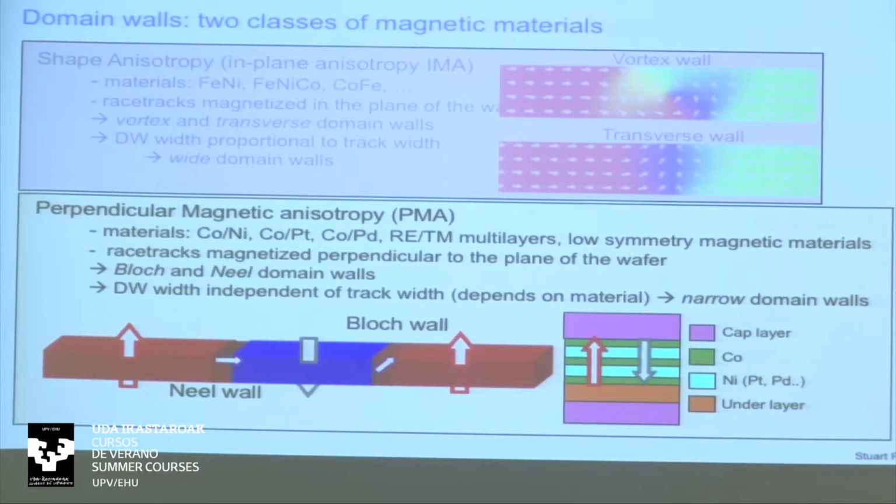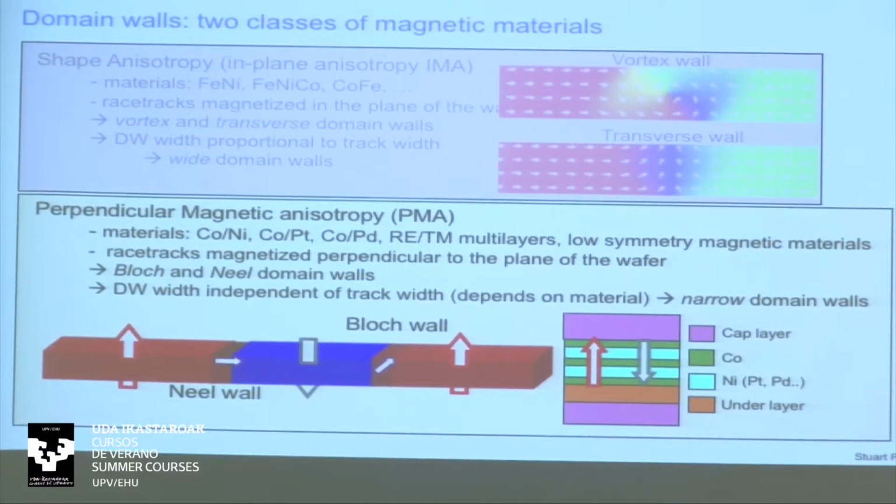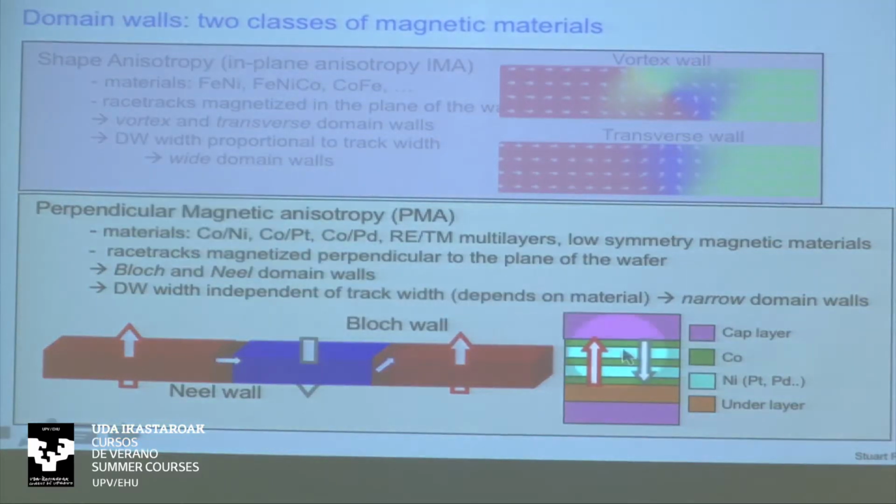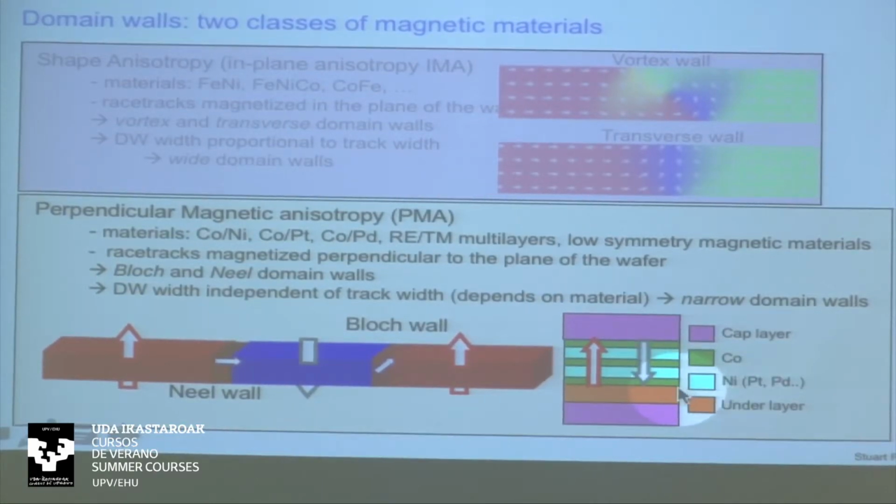So it turns out, I want to discuss this. It's a little bit technical, but nevertheless, I think it's interesting. So you basically have a racetrack which consists of these wires. The green is cobalt. These are like 1 to 3 angstroms thick, separated by nickel, which is about 7 angstroms thick, so just a few atomic units thick.